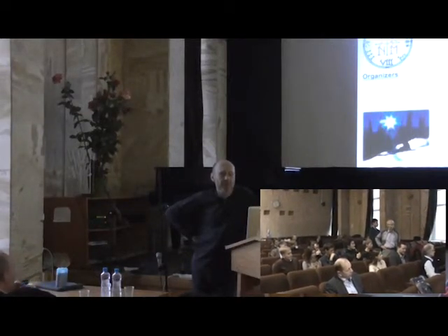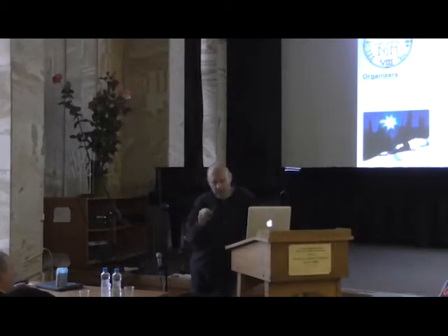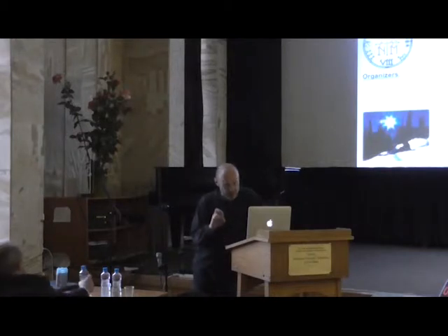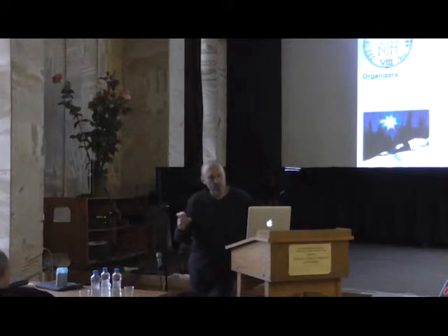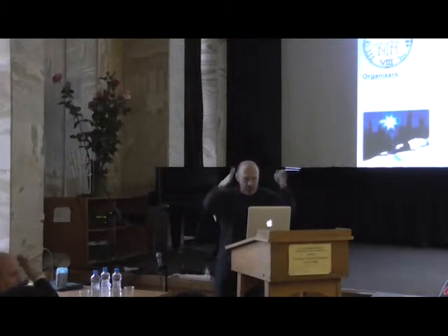Yes, the question is how small the structures can be, and can we really use the electron beam, if I understood correctly, to make that? Basically, the answer is yes. But still, for example, bond rotations induced by the electron beam are some sort of random process. But nevertheless, you can focus your electron beam now into an area of about 1 angstrom. There is still some spread of the electron beam, but we're talking about less than 1 nanometer.